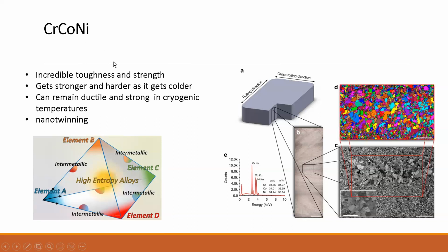So this specific alloy has been recorded by certain studies to be one of the, if not the, toughest materials on Earth. It is much tougher than titanium or nickel-based alloys or other alloys, and it actually gets stronger and stronger, harder, and tougher as it gets colder, and it can operate at 20 Kelvin, cryogenic temperatures, at which other alloys or materials go from ductile to brittle and experience catastrophic failure. This material, however, does not do that. It remains ductile, it remains strong, and actually gets stronger.